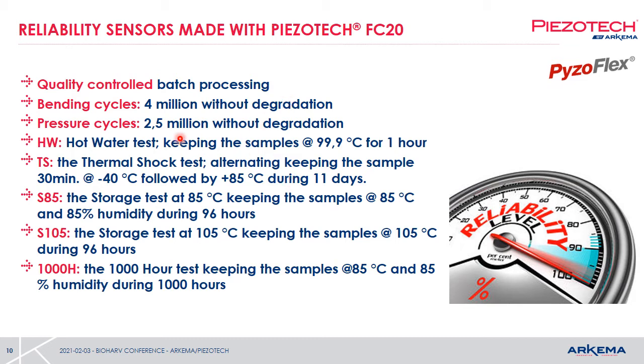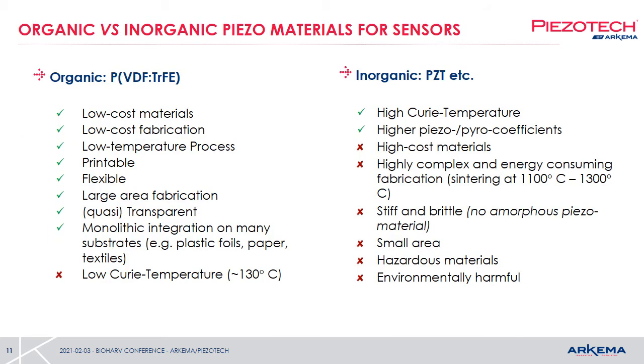Especially, let's say, stability in high humidity tests, so hot water, high humidity, high temperature, because fluoropolymers are also known for some adhesion issues. When you print sensors, we do not meet these kinds of issues. Also thermal shock cycling. So it meets especially the automotive and consumer electronics standards. And PVDF is not able to meet this kind of standard, especially due to a temperature limit of 80 degrees Celsius.